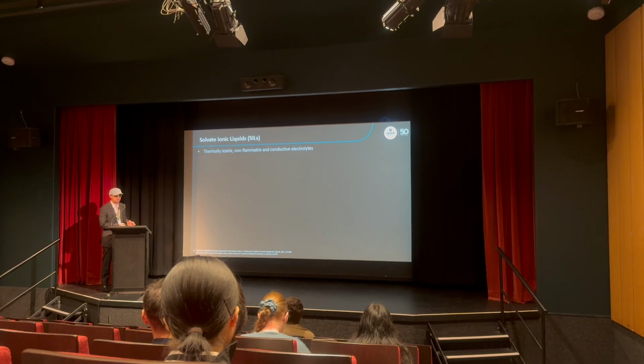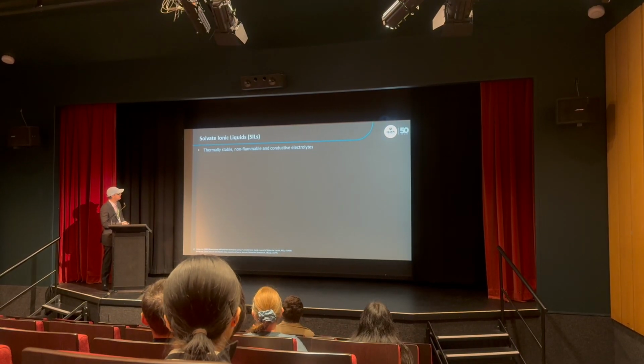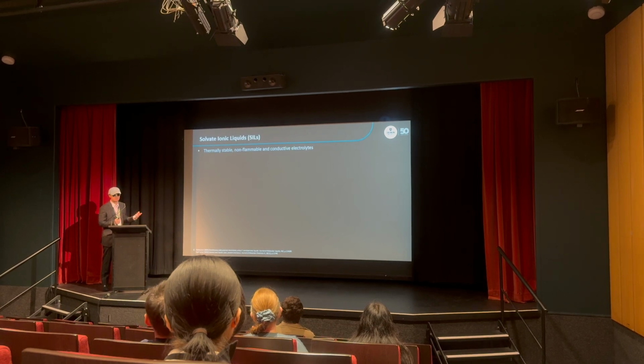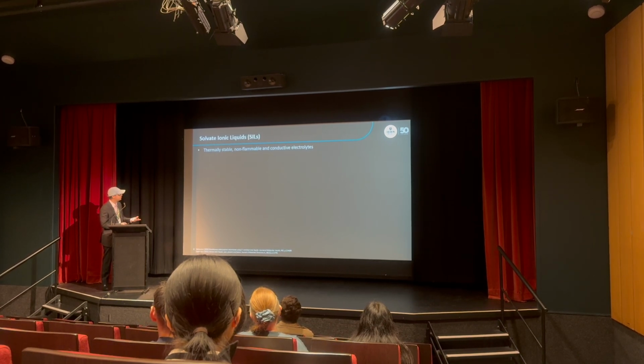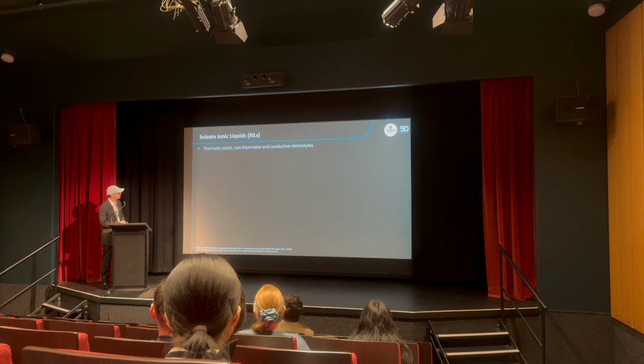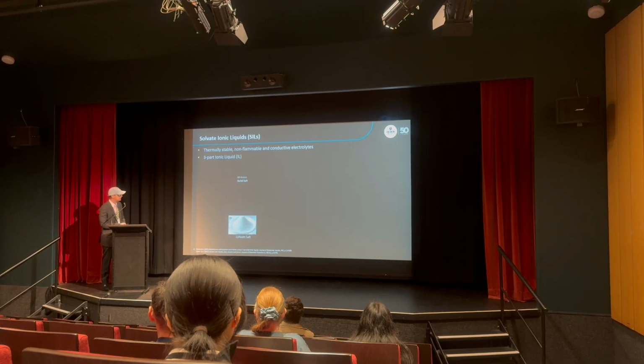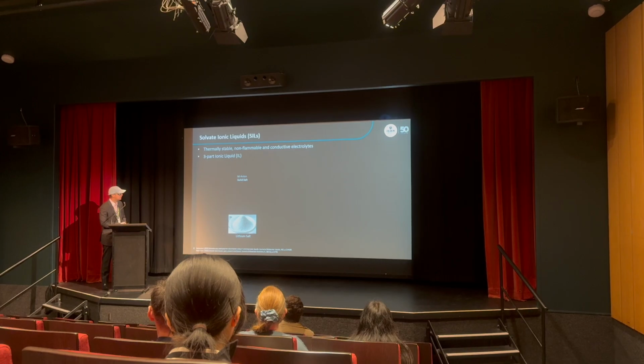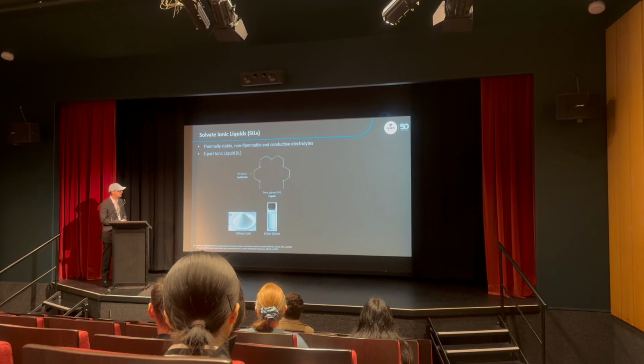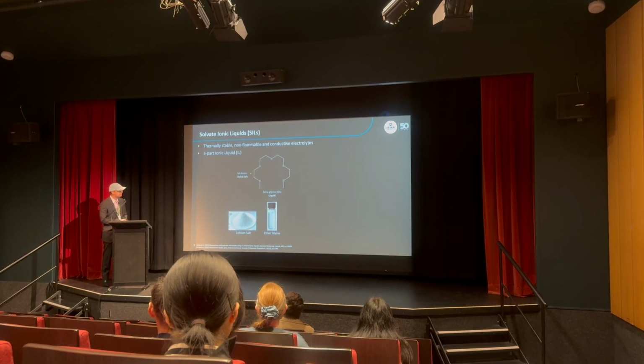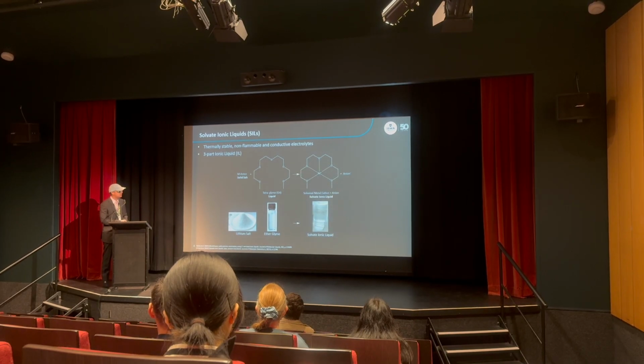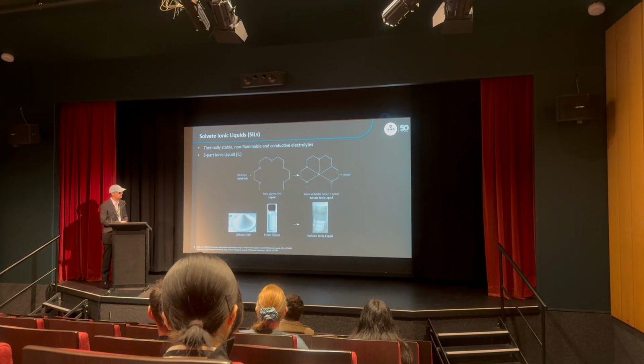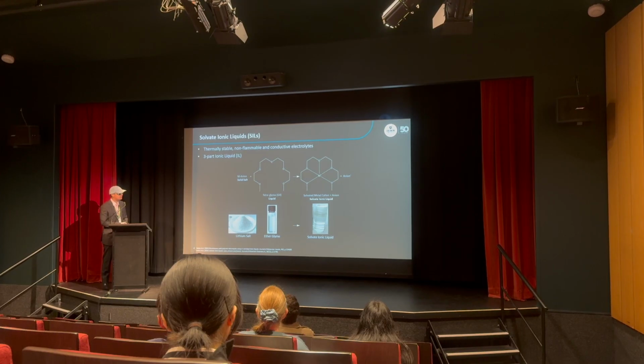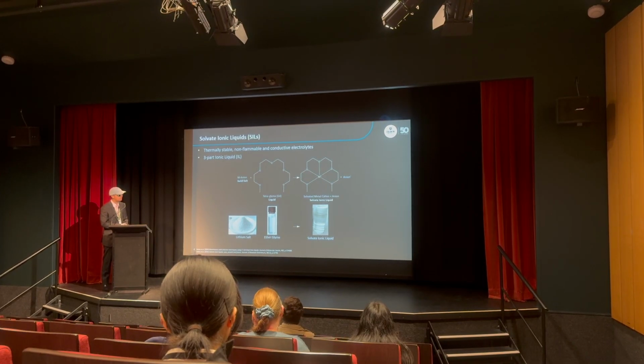For those who are unfamiliar with Solvate Ionic liquids, they obviously have properties consistent with the rest of ionic liquids of being thermally stable, non-flammable and conductive electrolytes. They are a three-part ionic liquid. They consist of a solid salt that is dissolved in an ether ligand. The cation in the system is chelated and solubilized by the ether ligand, and the anion in these systems is a pseudo-spectator with a diffuse charge.